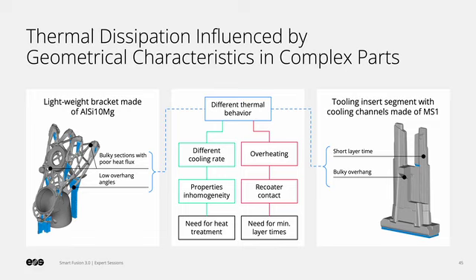The second critical aspect of the thermal history in laser powder bed fusion is the overheating over the build height. This causes super elevation of parts, which can lead to recoater contact and, in the worst case, interrupted or failed build jobs. A common solution to prevent this is to introduce a minimum layer time, which gives the material enough time to cool down after a layer is exposed. An obvious downside to this is that it increases build time and results in higher cost per part. Later on, we will also take a quick look at how minimum layer times can affect the microstructure.